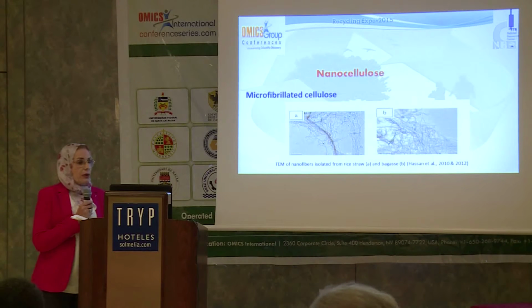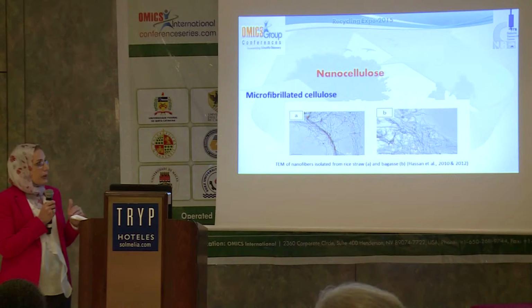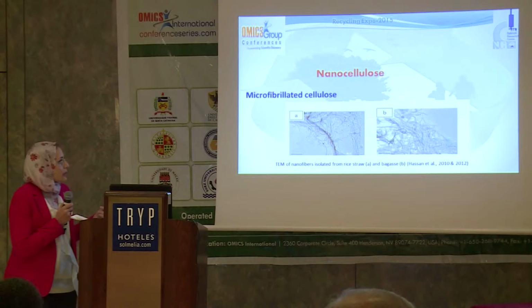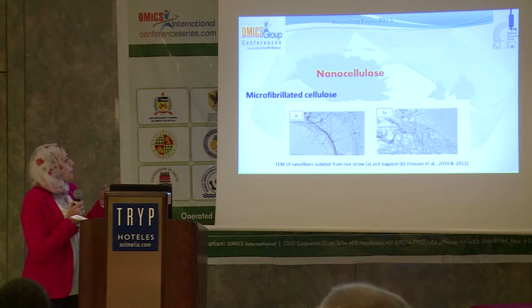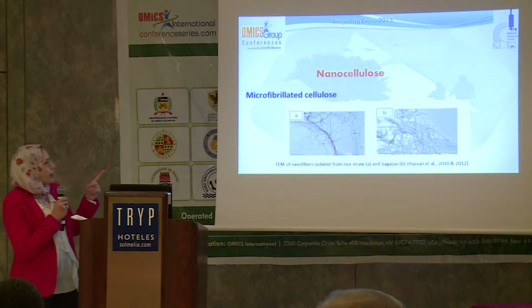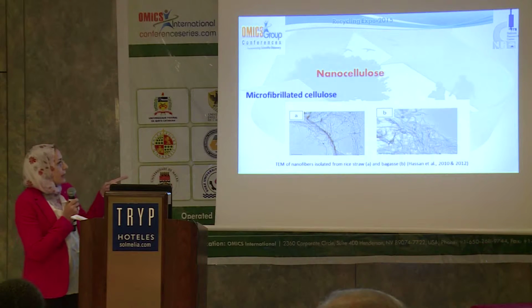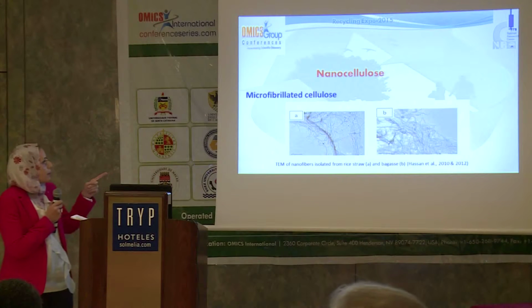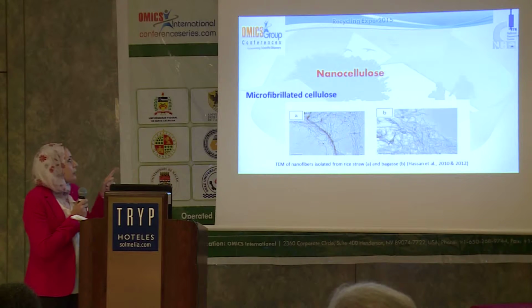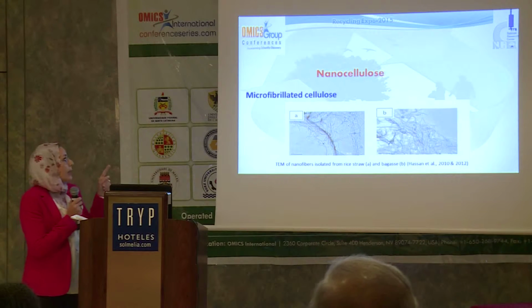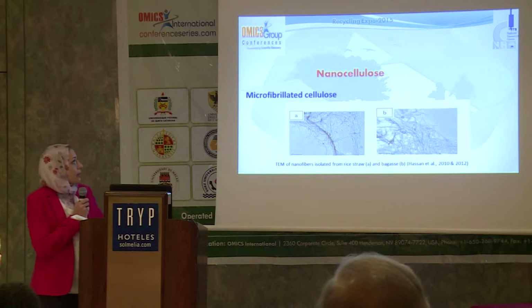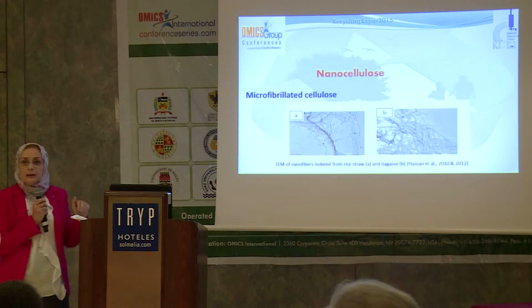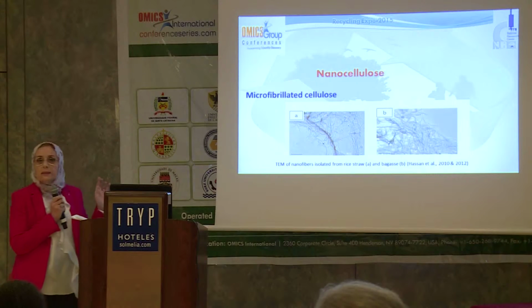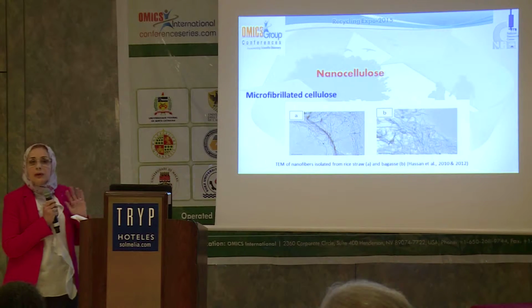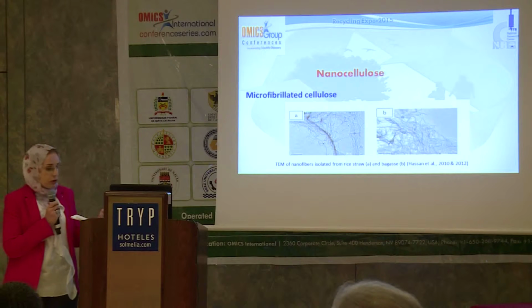In our lab, we have worked on nanocellulose, cellulose nanocrystals, and microfibrillated cellulose since 2008. Here is the microfibrillated cellulose prepared from the agriculture waste sugarcane bagasse and rice straw. Its dimensions are from 2 to 10 nanometer width and several tenths of microns length. It is prepared by mechanical treatment. The benefit is that no chemicals are used for its preparation, but it's energy consuming.